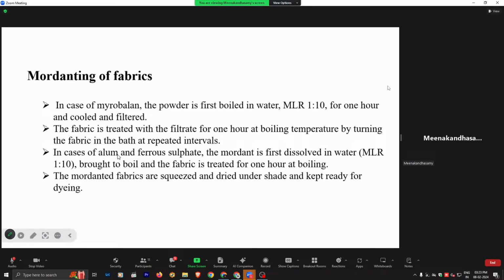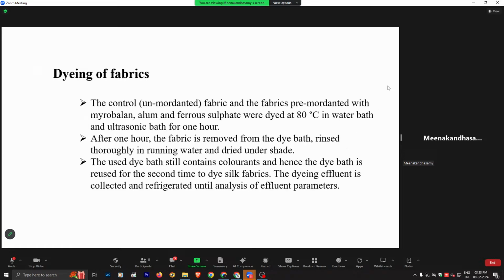Then for alum and ferrous sulfate, the mordant is first dissolved in water. The ratio was 1:10. It is brought to a boil and the fabric is treated for 1 hour at boiling. The mordanted fabrics are squeezed and dried under shade and kept ready for dyeing.